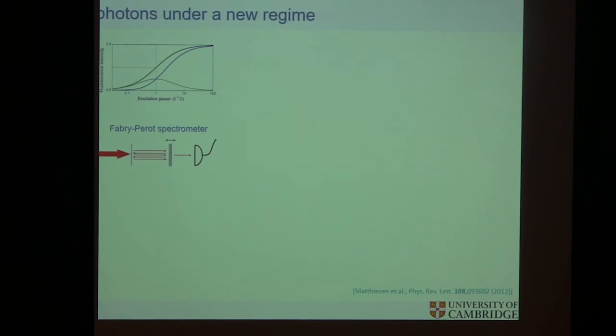Okay, so that's good, that's encouraging. So I'm getting laser photons back as elastic scattering. Maybe that could be something. So if you look at this, this is excitation power versus fluorescence intensity. You have two components, the incoherent component, the blue, and the coherent component, the green. The black is the excited state population. So you can reach half that in steady state.